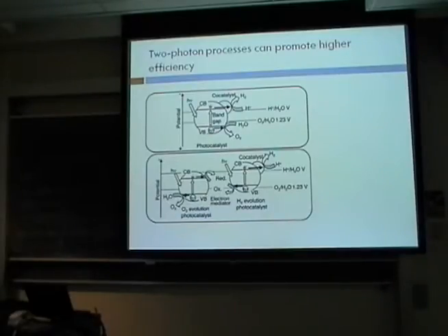Okay, so there are ways to try to use different oxidation-reduction reactions that are at an intermediate potential, in between the potentials of the proton reaction and the O2 reaction, in order to get an appropriate driving force, and with not too large of a band gap so that you can use visible light to do the excitation. And there are a lot of more complicated schemes than this to try to do that. But this is actually a pretty popular one right now.